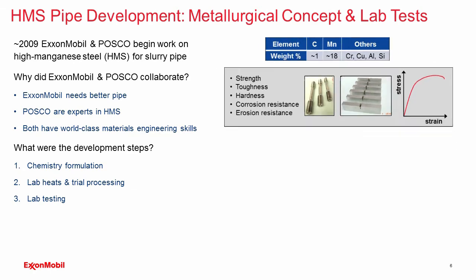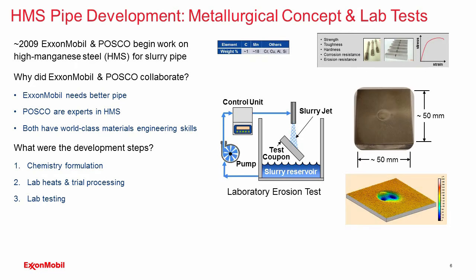We had a laboratory test to measure the erosion resistance. You can see there the pumping of a slurry jet. This is water mixed with sand product that impinges on the test coupon. And then the coupon shown on the right, you can see that impingement area, and the basic metric measured in this test is weight loss.